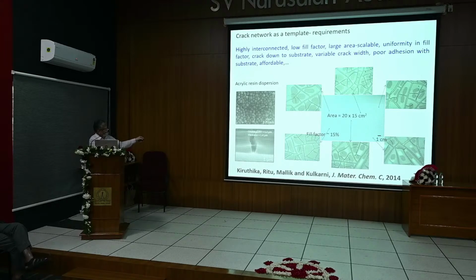This is the real experiment. You see the photograph of an area of 20 by 15 centimeter square, coating of this particular particle system, and the solvent is taken away, and the dried system is here. And wherever you put the optical microscope head, you can see lots of these cracks there. So the entire system is now having an interconnected crack system, much the way what we saw with the lake bed. And you can calculate the fill factor of the cracks, that's around 15%.